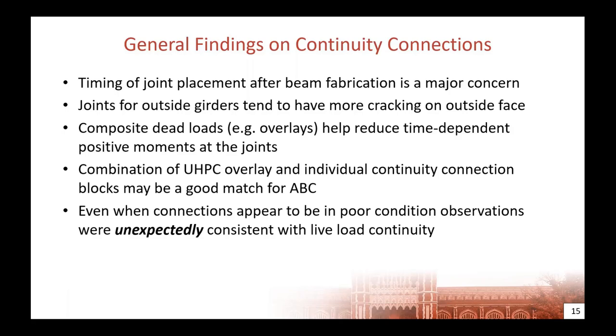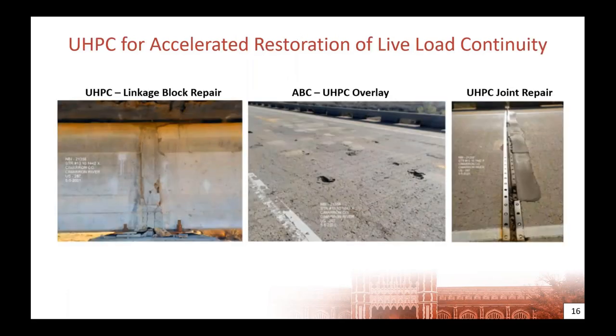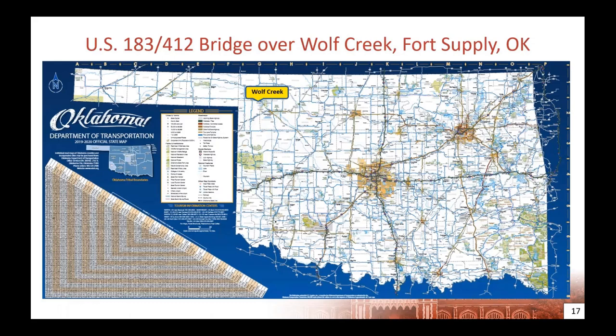shrinkage that's time dependent. So if you have the opportunity to use an ultra high performance concrete in connection in combination with linkage block repair, that's the perfect ABC match. I mean, here we have a bridge with poor concrete. It's having deck issues, maybe beyond hope. It's having linkage block issues. It's having joint issues. It could be, I think, a candidate for an accelerated bridge construction using lots of this UHPC technology. And it's something I wouldn't mind trying.